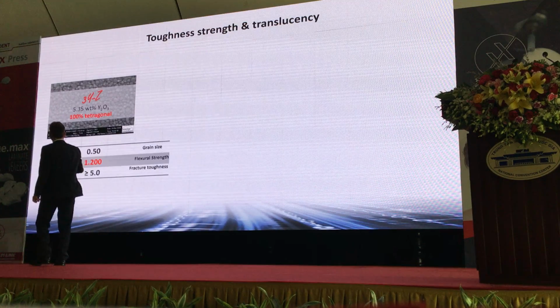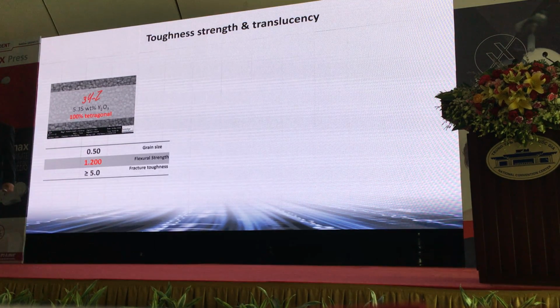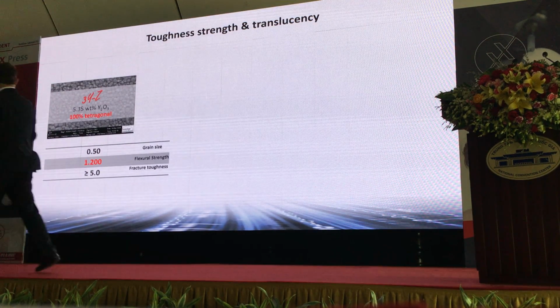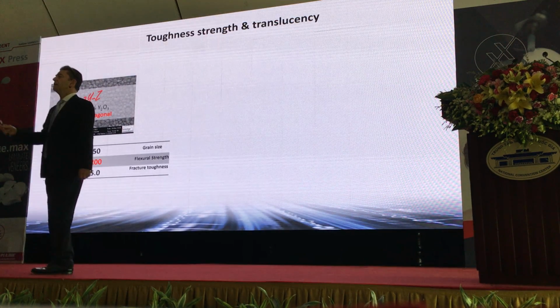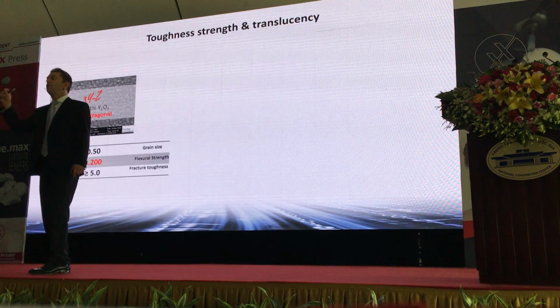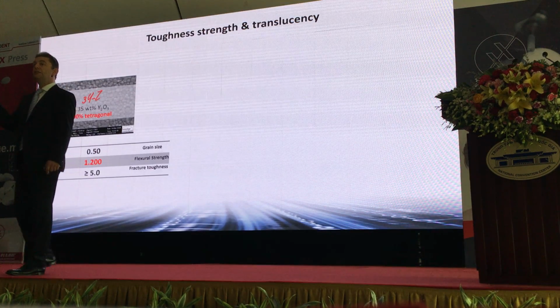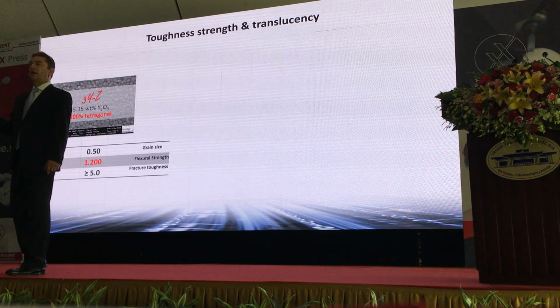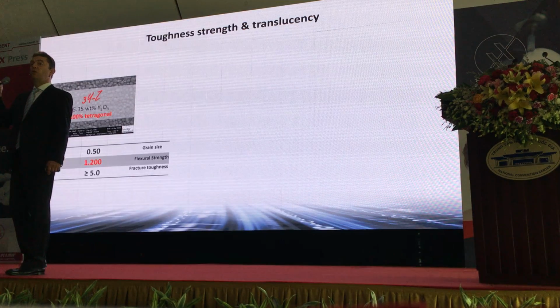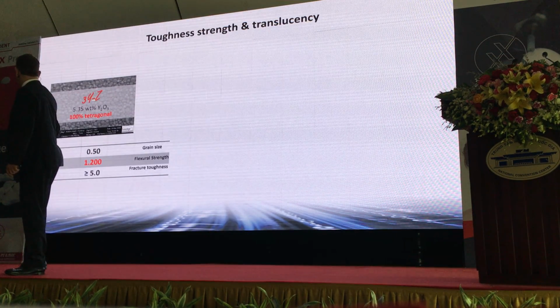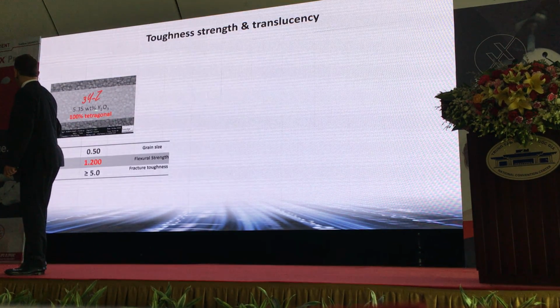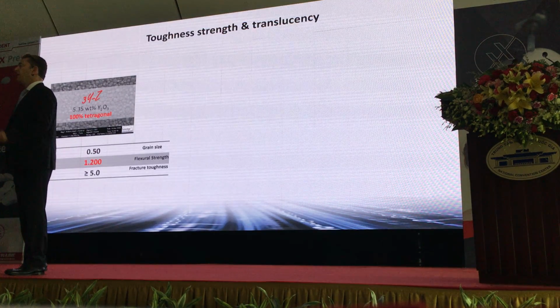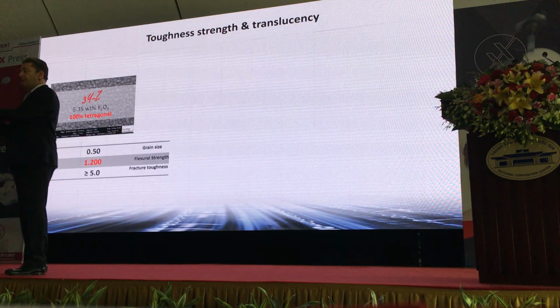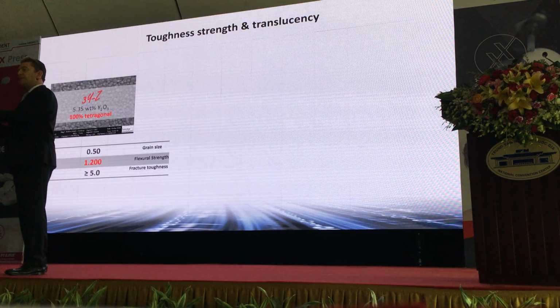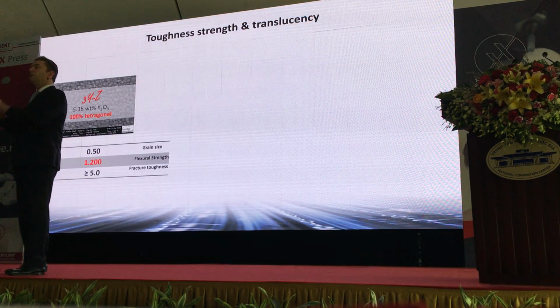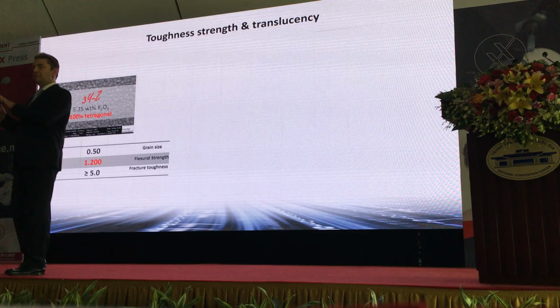And this is actually 3YZ zirconia. That means we have about 3 mole percent of yttrium oxide inside this zirconia. So we have 100% of tetragonal polycrystals, which is very good for the strength, but not so good for aesthetics, because this material is quite opaque.